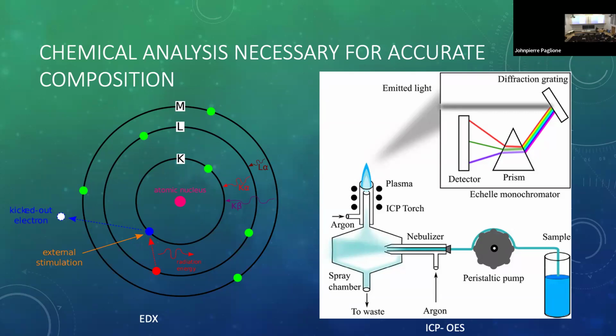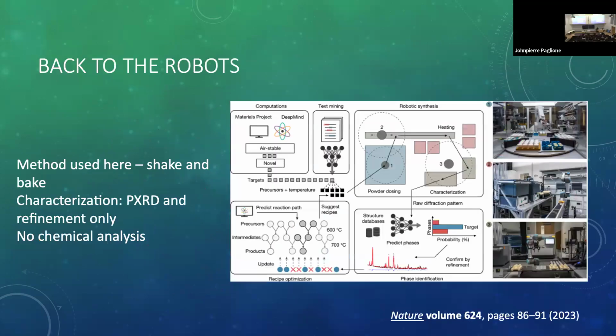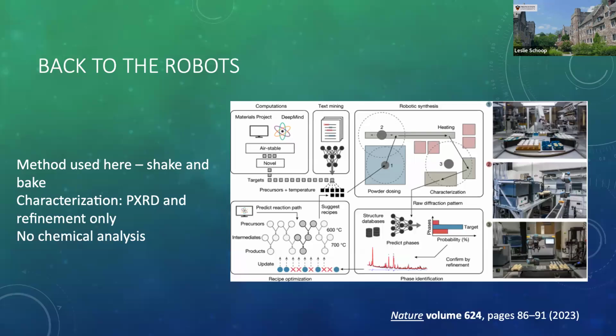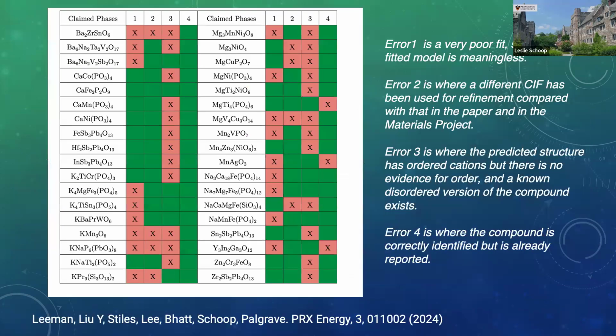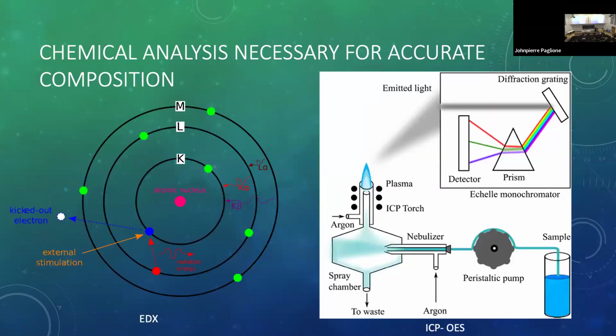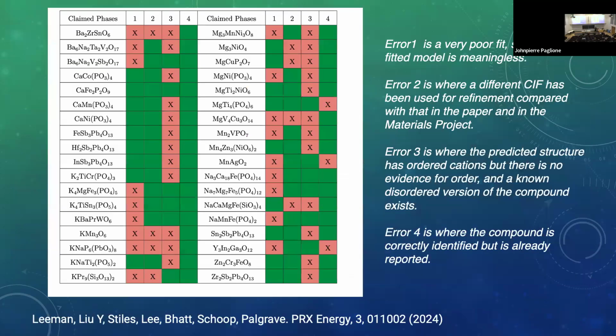Okay, there's a lot more to say about it, but I'm going to cut it short. I just want to go back to the robots and tell you what went wrong. Again, the method they used to make these samples is shake and bake. The powder samples' characterization is powder X-ray diffraction and refinement only, and there wasn't any chemical analysis. So this is a table of these 43 compounds, and we identified 4 common errors. And you see that for almost all of them, at least one of these errors is present.